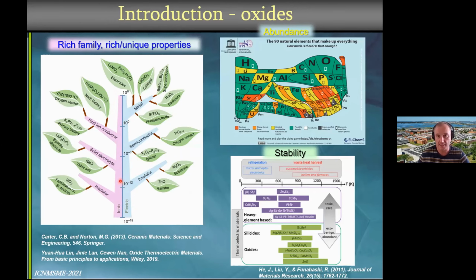In transition metal oxides, the transition metals themselves can have different oxidation states, and this gives rise to different oxide structures, and also different conductivity mechanisms, which can involve the movement of electrons, holes, oxygen ions, and of course some mixed cases. Oxygen itself is quite a widespread element, as you know, and it constitutes a significant part of each oxide.